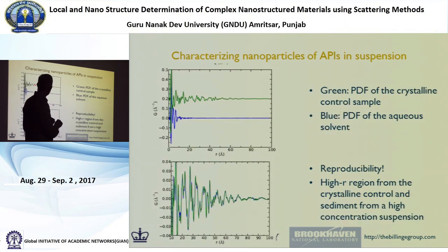So we can do a measurement. This is the signal from the drug itself. This is actually a dry crystallized powder of the material. So that's the signal from the drug. This is the signal from the liquid, the solvent that it's suspended in. So the solvent is structured. It's water, but it has some other things in it. And you can see these peaks down in the lower region below 10, and then it's flat.